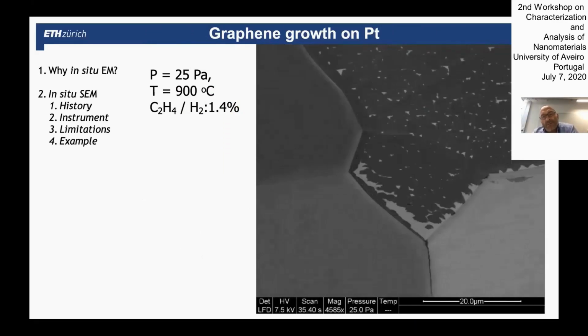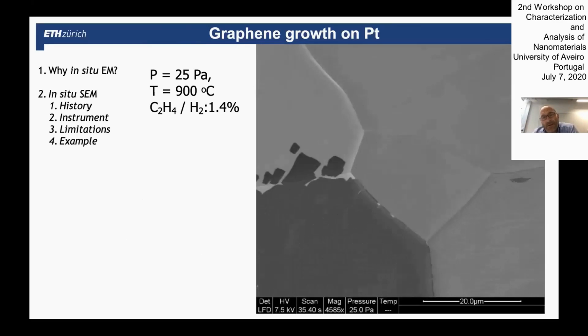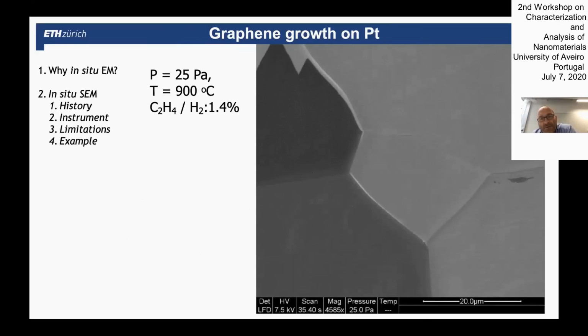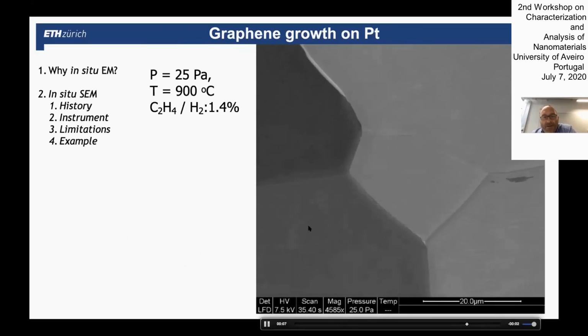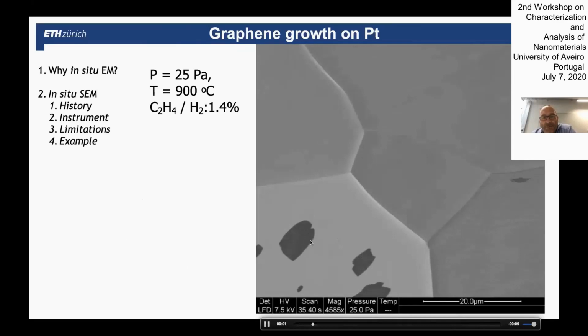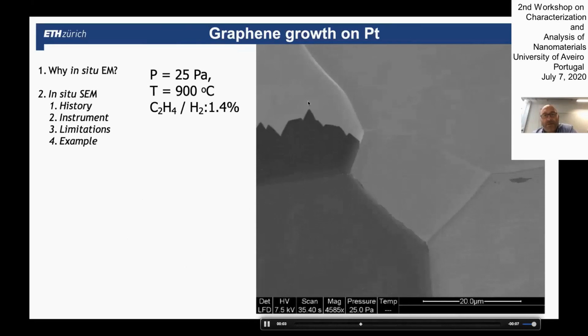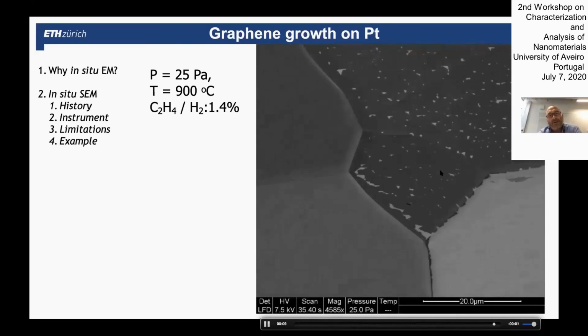So what we did here, we have a polycrystalline platinum, and we look at different grains. And by just running the reaction of graphene growth, you see some grains are very active, like this one. This is the first one that grows graphene. It spills over to the next. And the other grains are not active. We have to increase the hydrocarbon chemical potential in order to nucleate there as well.